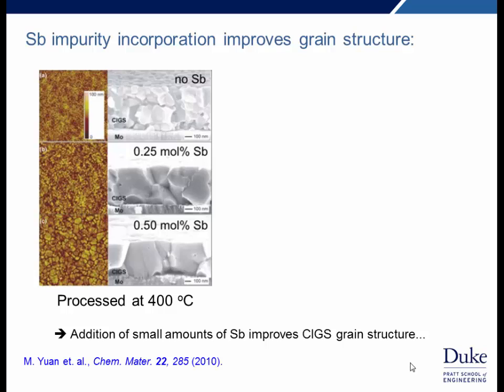Sometimes we don't want to heat up above 500 degrees C, for example, if we want to work with very low cost, low Tg glass, or maybe a polymeric substrate. And so we've looked at mechanisms for reducing the heating temperature. One of these approaches involves controlled incorporation of impurities such as antimony or bismuth. Here we see in this example that introducing as little as 0.5 mole% of antimony enables getting a grain structure that extends across the entire thickness of the film, even when processing at temperatures as low as 400 degrees C.